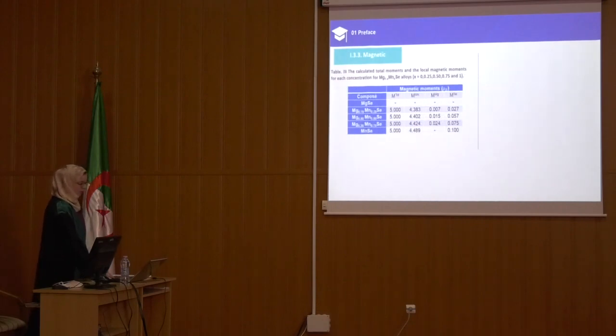Here we present the calculated total magnetic and partial local magnetic moment for each concentration, showing the value of the total and local magnetic moment. Through the table, we observe that the local magnetic moment of manganese-doped MgSe is reduced, less than the predicted Hund's values